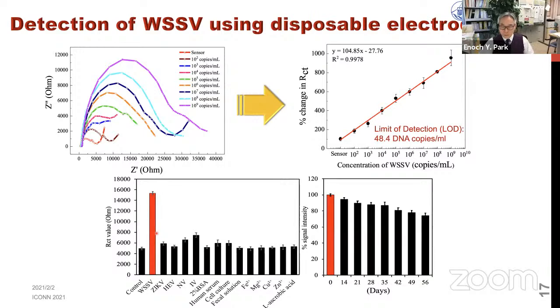And also, we have to check the stability here. We stored this electrode for 2 months. Here, until 1 month, the performance is very similar, with less than 10% decrease. Therefore, we think for 1 month, this electrode can be used to detect WSSV.